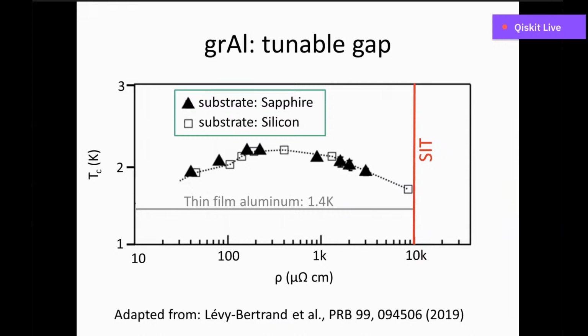And this is where granular aluminum again becomes a very good choice, because the critical temperature of granular aluminum, the gap of granular aluminum, can be tuned with its resistivity. As I showed before, we can easily tune the resistivity by tuning the oxygen pressure during deposition. The critical temperature will follow a dome-shaped behavior as a function of the resistivity, and it will always be above that of pure thin-film aluminum. If I make my circuits with granular aluminum, then I can use aluminum as my phonon trap, since it always has a lower gap.